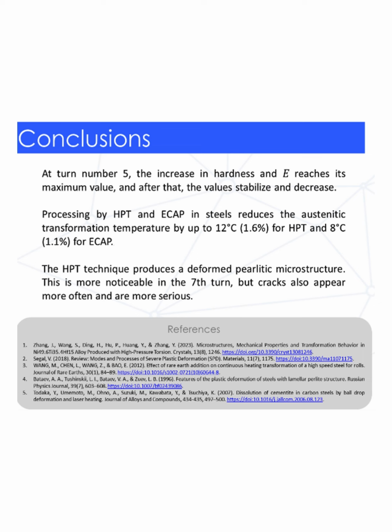As conclusions from this research, we have to note, at turn number 5, the increase in hardness and elastic modulus, E, reaches its maximum value, and after that, the values stabilize and decrease. Processing by HPT and ECAP in steels reduces the austenitic transformation temperature by up to 12 degrees, 1.6% for HPT and 8 degrees, 1.1% for ECAP. The HPT technique produces a deformed pearlitic microstructure. This is more noticeable at the 7th turn, but cracks also appear more frequently and are more severe.